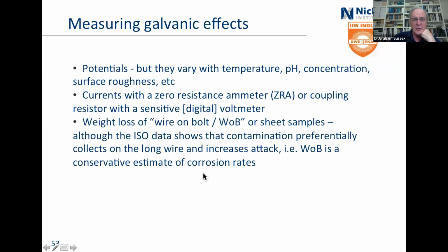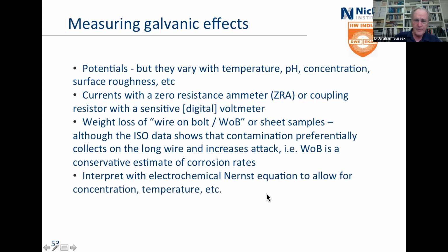You can measure it with wire on bolt, which is what the ISO people do. They use that for things like wire, aluminium wire, and so on. It preferentially collects contaminants along the wire in the crevice because it's wound on a thread, and so it gives a fairly conservative estimate. Or you can go away and do Nernst calculations and pretend you're an electrochemist.